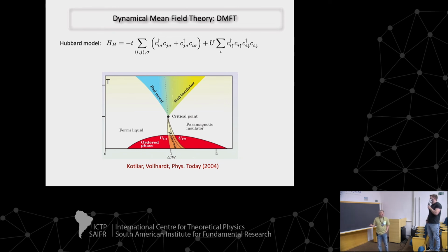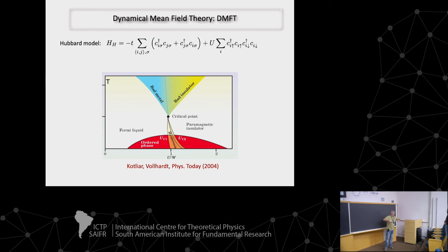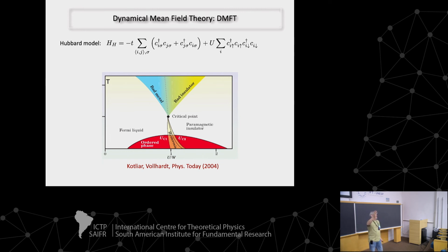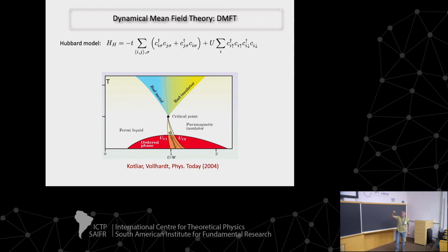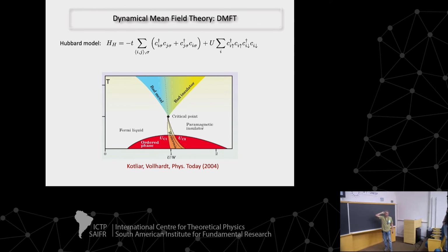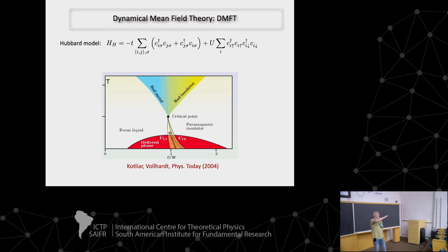Of course, depending on the way you solve the impurity problem, these lines are at different points. But you can have CTQMC, probably the state-of-the-art method for calculating this. You have an excellent curve. There is one important question, which is where this line is inclined, whether it's like this or like that. That's an important question, just like in water, right? Whether it's this or like that. And here, it's interesting because if you do an extension of dynamical mean field theory where you go from one site to a cluster, you change the slope. And this is known, the physics is known.